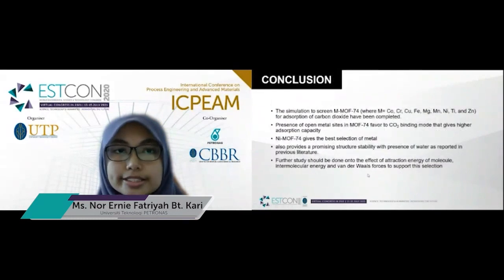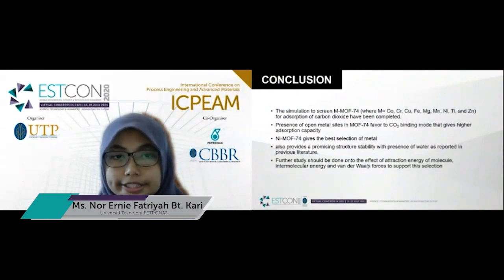As the conclusion, the simulation to screen MOF74, which consists of the transition metal and also magnesium, has been completed for adsorption of carbon dioxide, and the presence of open metal sites favors CO2 binding that gives higher adsorption capacity. And nickel MOF74 gives the best metal center and provides a promising structure stability in the presence of water, as reported by the previous literature.